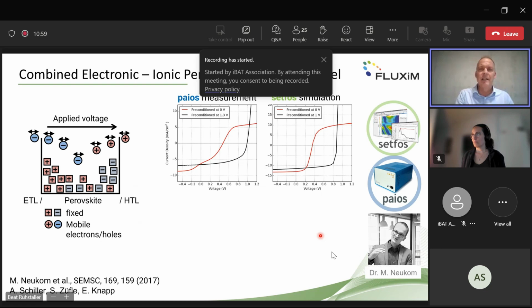Now, again, an example of a mixed ionic electronic charge transport device. Perovskite solar cell is an interesting device because it really also depends a bit on the history, how you have treated the device, if you pre-bias or not. And indeed, if you look at the current voltage curve of this solar cell, if you precondition at 1.3 volts, you get a nice solar cell JV curve. But if you precondition at 0 volt, the curve looks much different than the typical solar cell JV curve.